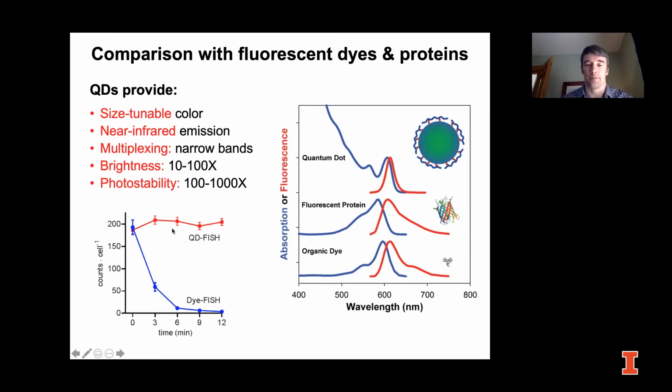With quantum dots, potentially you can image them for hours, sometimes longer than hours, continually. And dyes, you can't do that. Dyes typically will degrade. It's called photobleaching, and the actual reason for that is because they chemically change, usually because of oxidation or hydrolysis. So they'll actually degrade. Quantum dots don't have a tendency to do that under excitation.